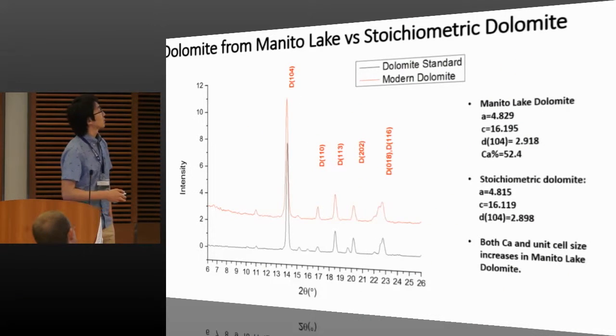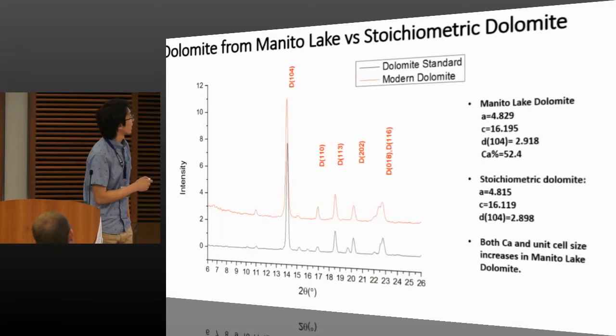And take a closer look at the dolomite here. This is the dolomite we got from the lake, and this is a standard dolomite X-ray diffraction pattern. And you can see that it's missing a peak here. That's the 015 peak. That's the peak indicating the ordering of the dolomite. So that tells us our dolomite is really young and really disordered. But XRD cannot tell how disordered that dolomite actually is, so we need later analysis for that.